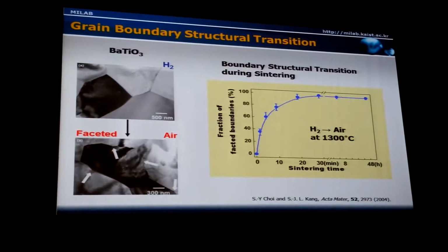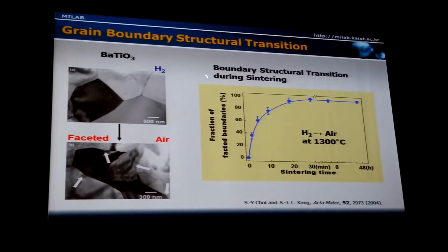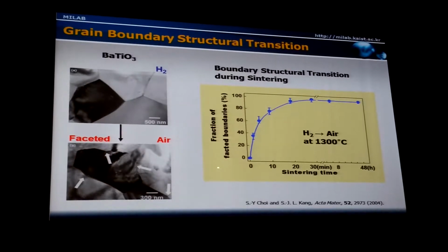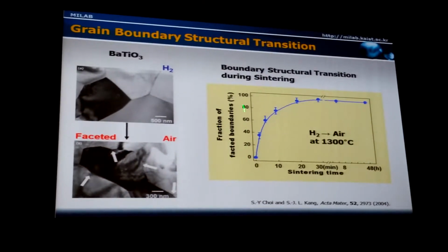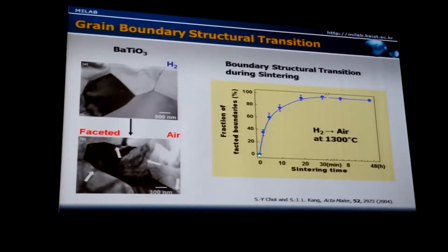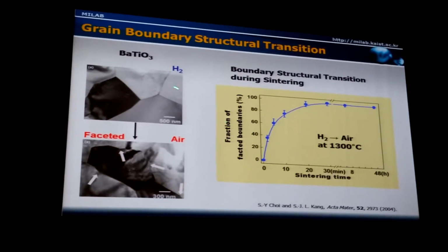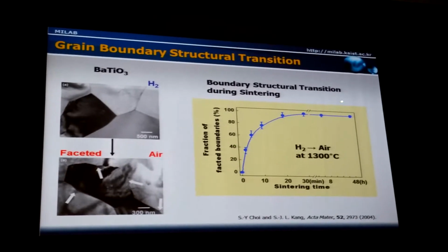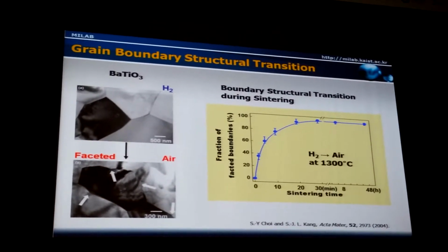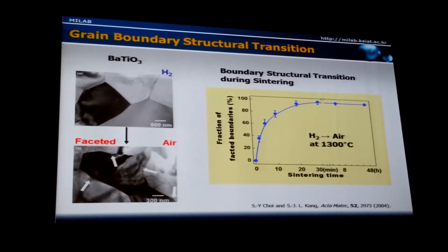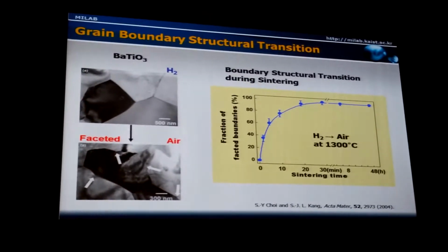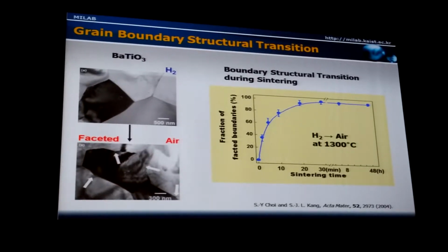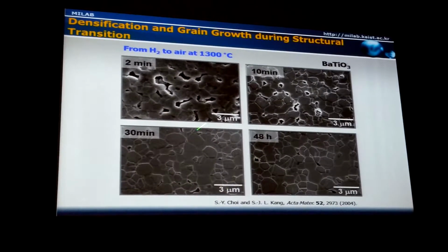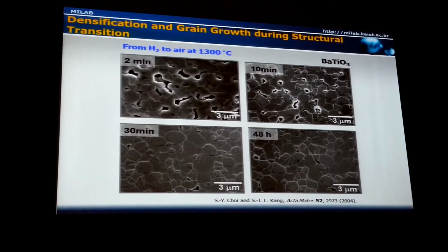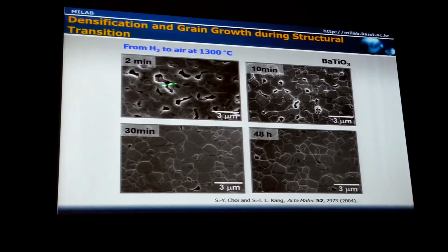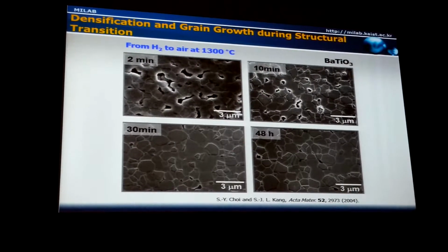We did a model experiment, in which we simply changed the oxygen partial pressure from hydrogen to air in barium titanate, and measured the fraction of faceted boundaries. The fraction of faceted boundaries was almost nil in hydrogen, but it increases rapidly and becomes almost 100%. All the boundaries are faceted in about 30 minutes because of the high diffusion rate of oxygen in barium titanate. Then we observed the microstructure after changing the atmosphere from hydrogen to air, at 2 minutes, 10 minutes, 30 minutes and 48 hours.